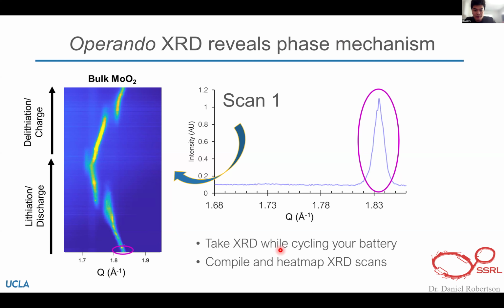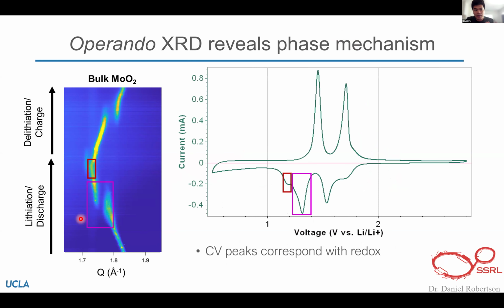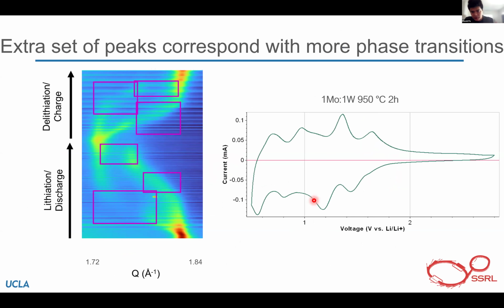Okay, and so this is an example of just pure MoO2. And so looking at some of our solid solutions, we can see that we've modulated the phase behavior. Oh, and this is just to show that, again, these phase transitions can be correlated with redox events in our cyclic voltammetry. Okay, and so looking at some of our more phase-separated solid solutions, the takeaway from here is that we have increased the amount of phase transitions that are present. In fact, we can see a molybdenum-rich and a tungsten-rich phase reacting separately. And again, we don't want phase transitions. That's known to limit our material performance as well as to cause more degradation.